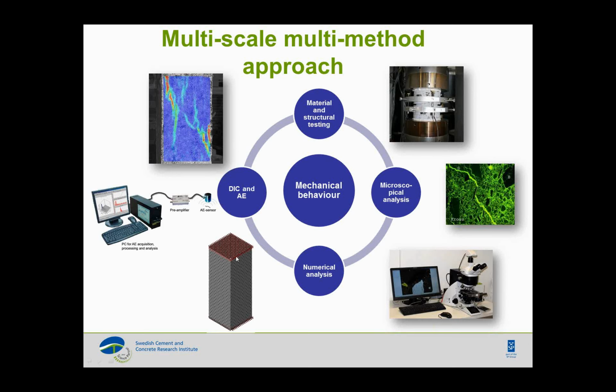And at the end we did numerical analysis of full columns, knowing how much expansion we have and how the expansion is distributed across the cross-section, and then running full-scale analysis on that. A little bit about the preparation of the piles. So we brought them to the lab. We cut one part of the pile as stub pile specimens for the full-scale testing, but the rest of the pile was used to core out a few cylinders, and for those cylinders we tried to put them under compression and in tension, and try to understand the behavior of concrete in tension and compression. We also used the same specimens for microscopical analysis to understand how much expansion we have had due to sulphate attack in these cases.